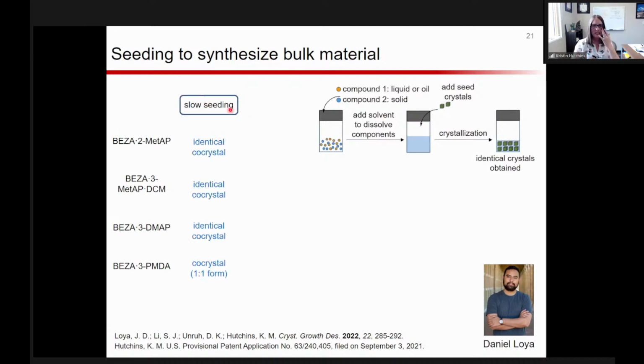And so we did slow seeding, where we allowed that crystallization to happen over a long period of time and did less concentrated solutions and got identical co-crystals in the top 3. And this is actually how we finally isolated that 1-to-1 form of the 3-PMDA. We also did fast seeding, where we sped up that crystallization time, used more concentrated solutions, and get identical co-crystals. And then interestingly, when we speed up that time, we actually get this mixture of the 2-to-1 and 1-to-1 form. So they are, again, sort of competing in solution.